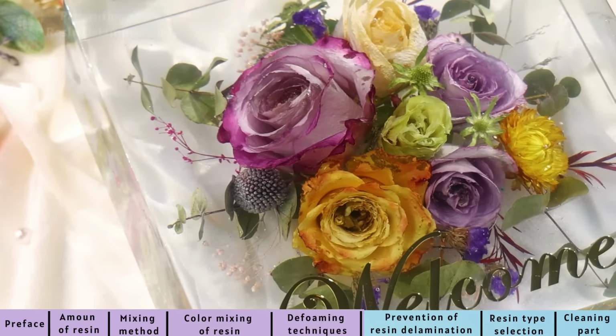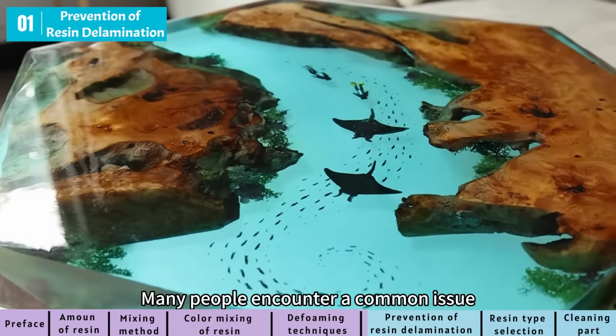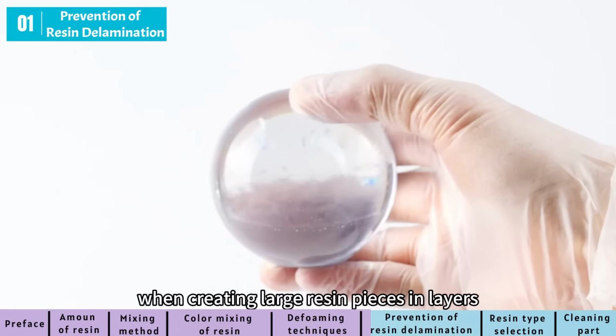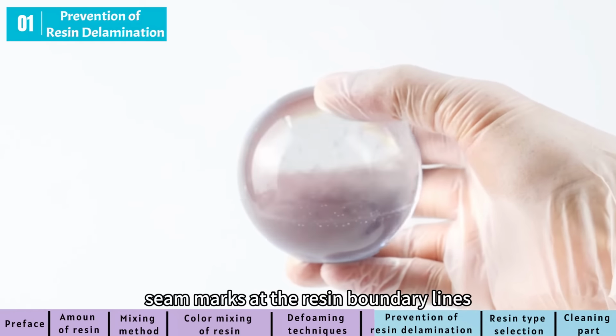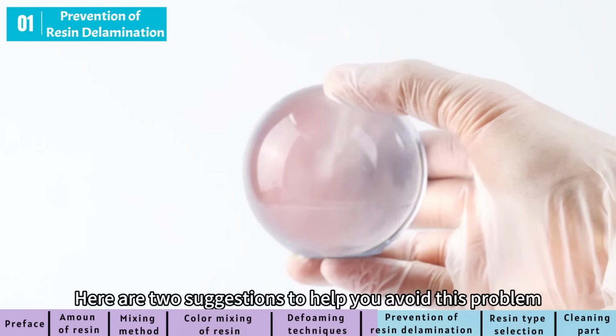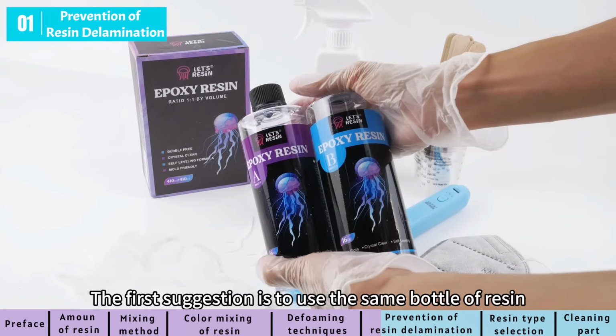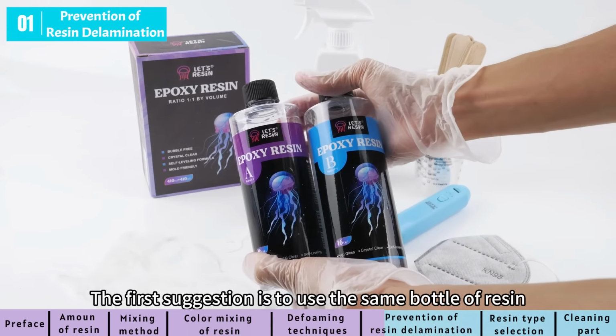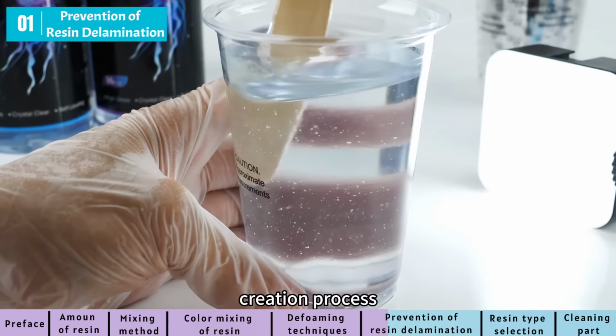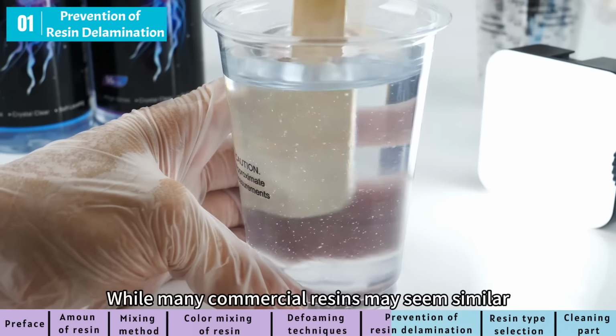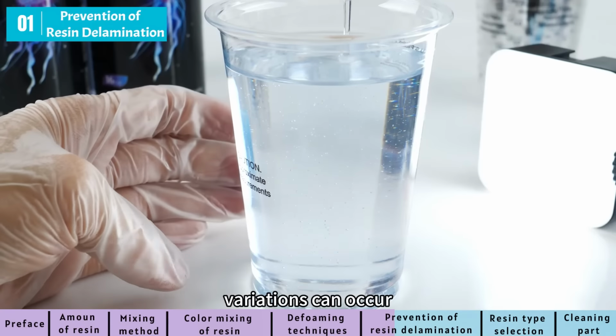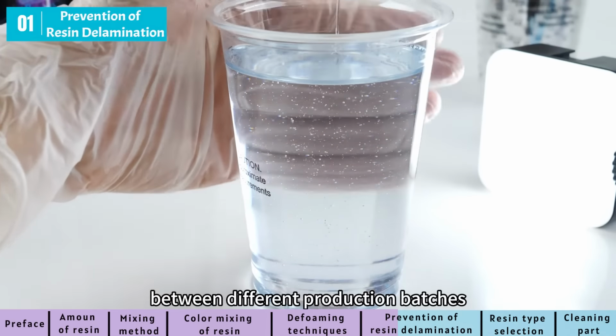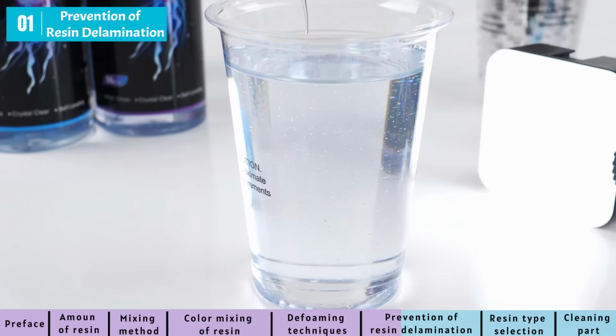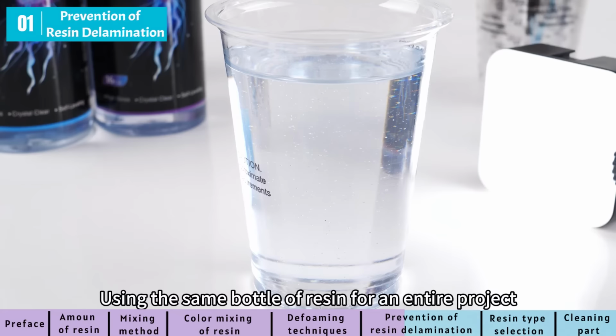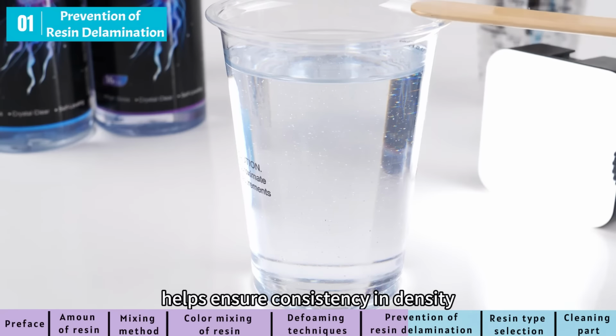Prevention of resin delamination and resin type selection. Many people encounter a common issue when creating large resin pieces in layers. There are noticeable seam marks at the resin boundary lines. Here are 2 suggestions to help you avoid this problem. The first suggestion is to use the same bottle of resin throughout the entire creation process. While many commercial resins may seem similar, variations can occur between different production batches, leading to slight density differences. Using the same bottle of resin for an entire project helps ensure consistency in density.